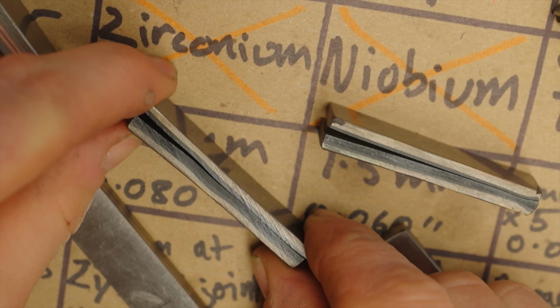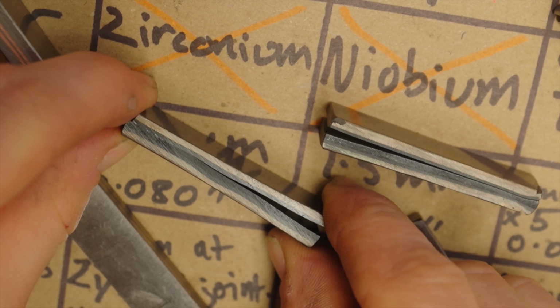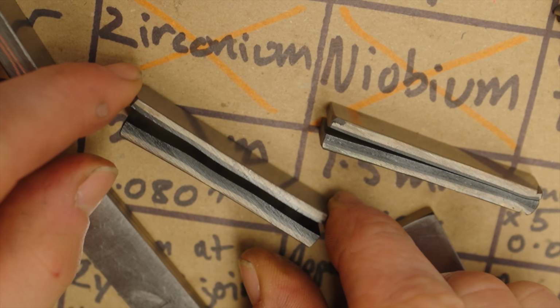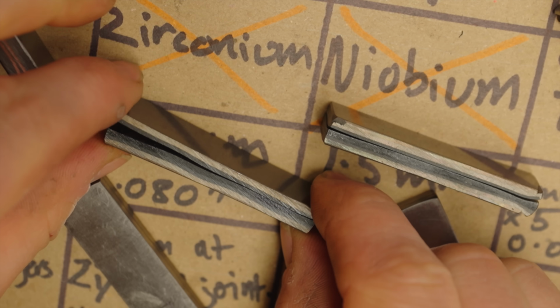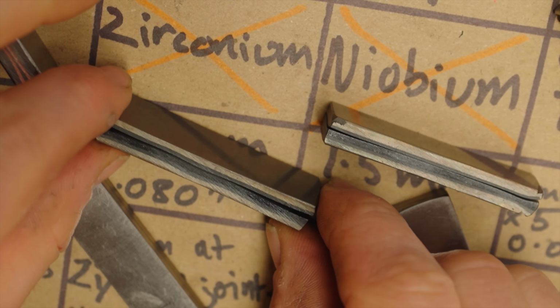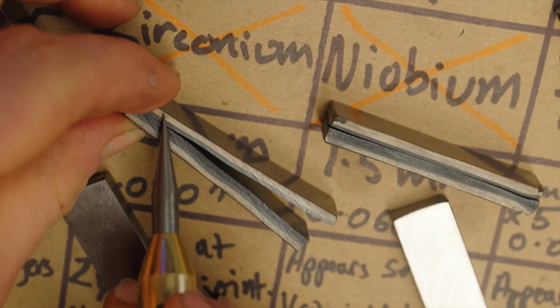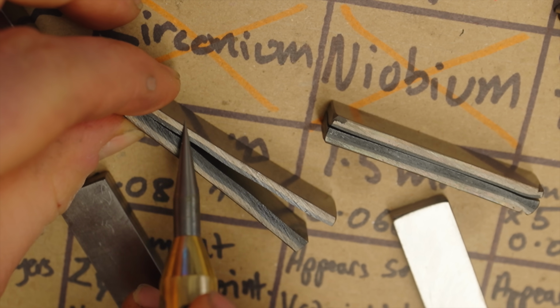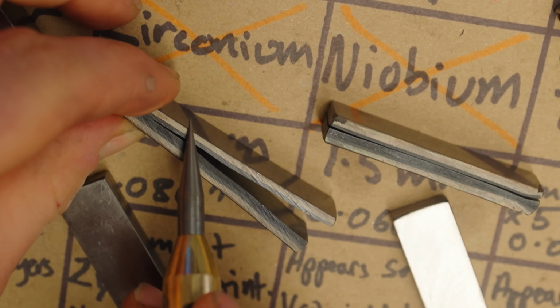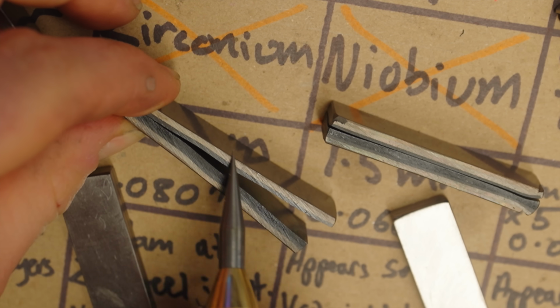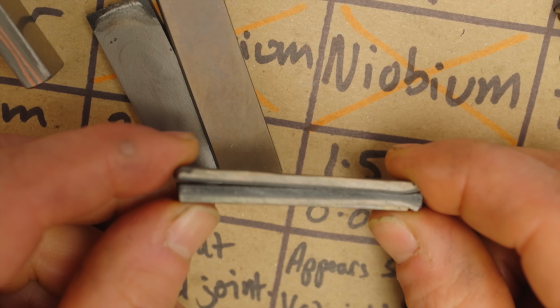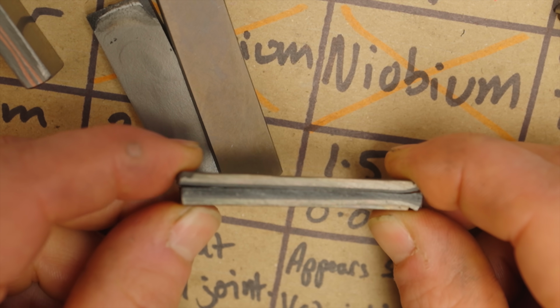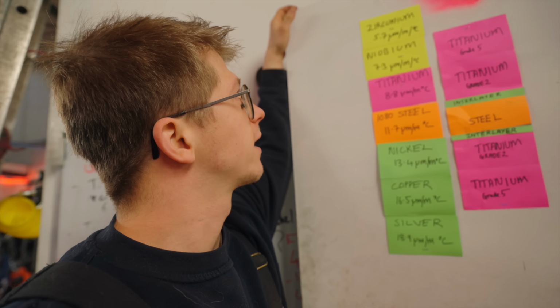There must have been some crazy stresses in the material, because after it broke, look at the shape that it's taken. It ripped itself apart because clearly the internal stresses were enormous. And I think that this outer layer here, which would have been our titanium, was in so much tension that it just plook. It's similar, but to a lesser extent on the niobium as well. Let's try and work out why.